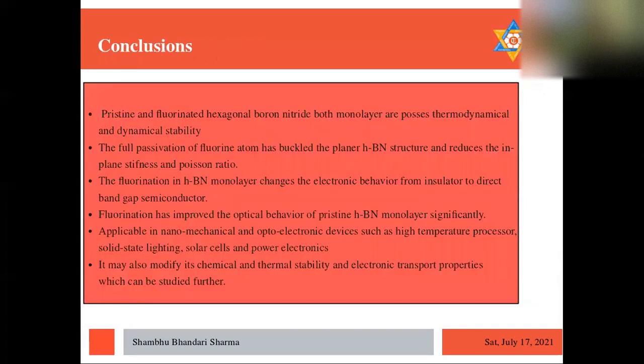And now the conclusion part, we conclude that both structures are thermodynamically and dynamically stable. And after fluorination, the planar structure of the boron nitride is turned into the buckled structure. And the electronic behavior also changed from insulator to direct band gap semiconductor after fluorination.